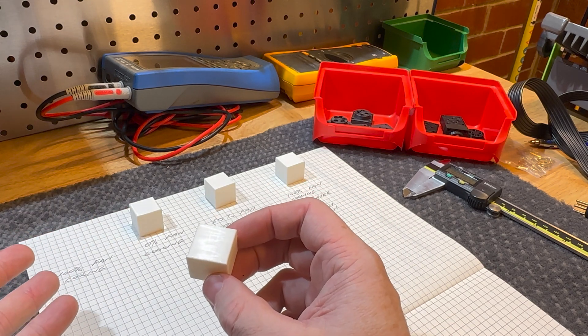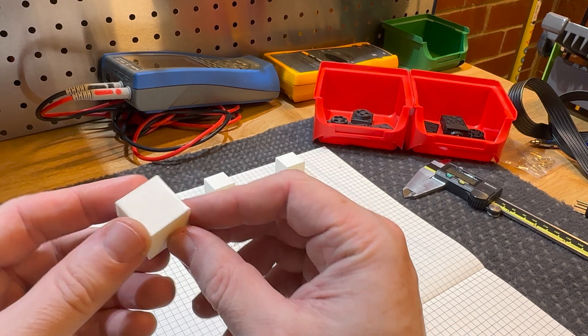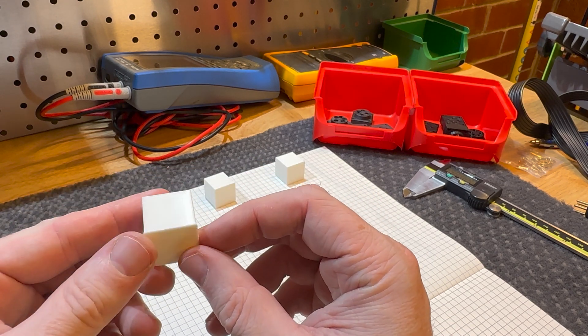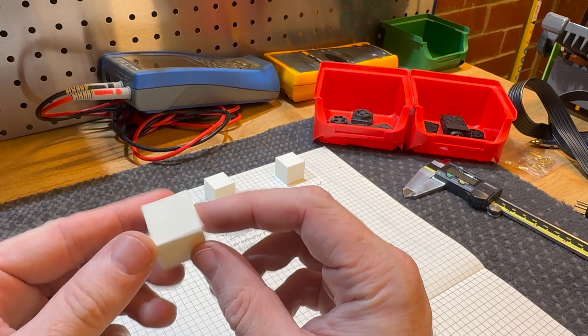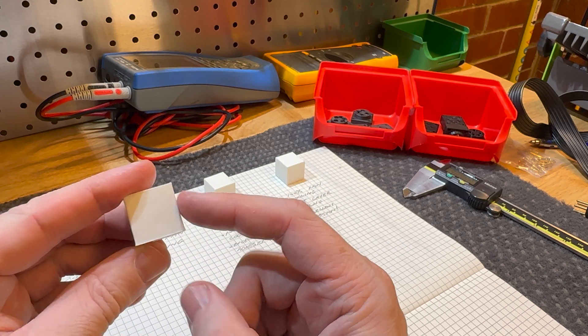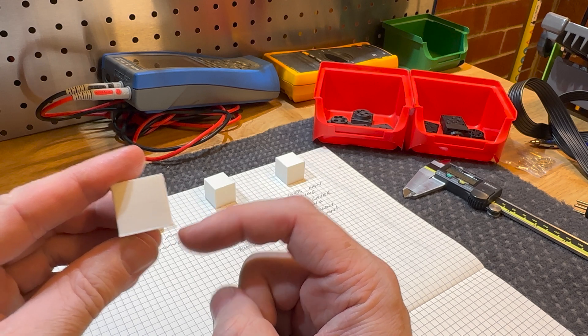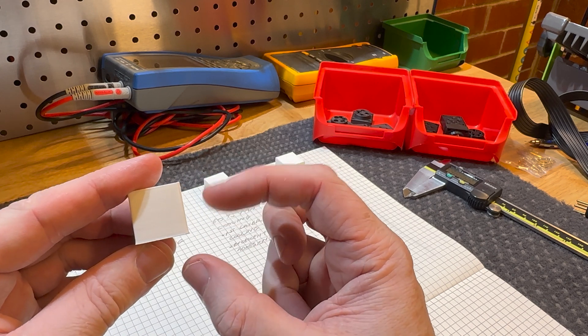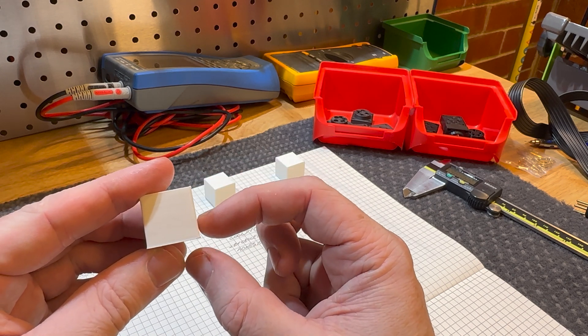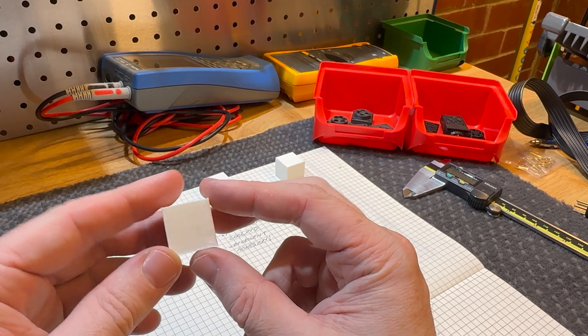So 100% fan cooling for the part, and overall for a first print, it went really well. There is, however, a bit of an elephant's foot at the bottom—it's sort of either squashed down or pushed out on the bed.